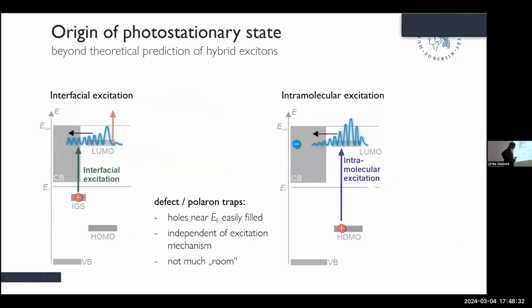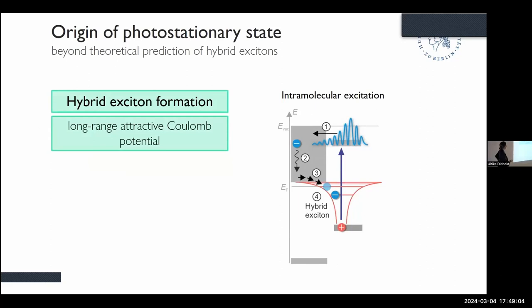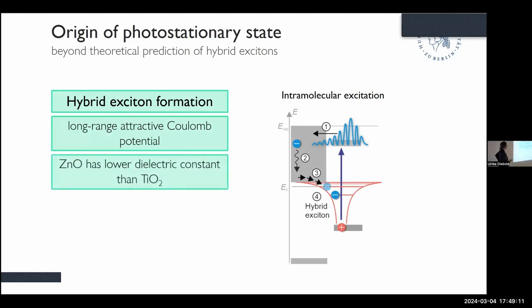There is not much room for such electron attractive states between conduction band and Fermi energy. If it's holes here in this region that we photo-induce, they would be easily filled because it's in the region of the Fermi energy. And our observation is that it's not independent of the excitation mechanism. Now we need the hole on the molecule for the electrons to come back to the surface. So it's the long-range attractive Coulomb potential of the hole that gets them back. And the reason why this works in zinc oxide and not in TiO2 is that zinc oxide has a much lower, more than a factor of 10 lower dielectric constant than TiO2.